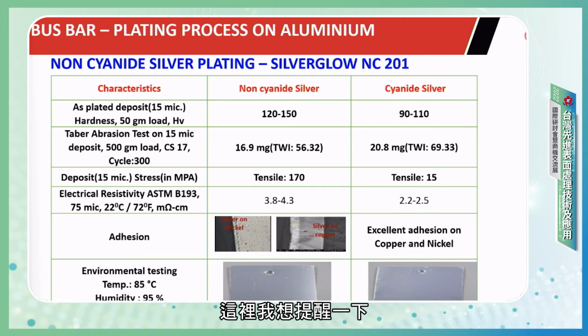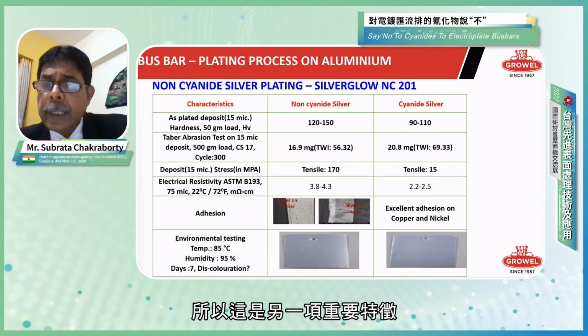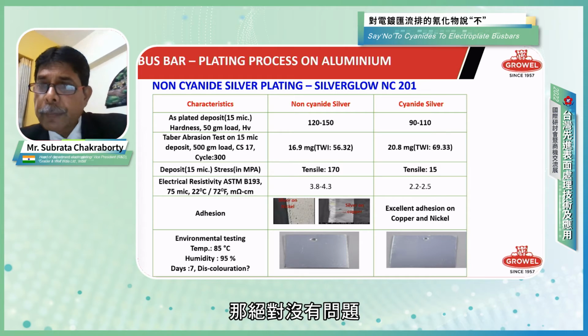One thing I'd like to mention here is that the cyanide silver I'm referring to is a deposit free from any additives, so it is dull with no additive system. If you use an organic system, you will be in this range, but if you use a metallic type brightener containing some selenium, it will go even closer to this. So this is another important characteristic, but if we heat treat it, there is absolutely no problem.